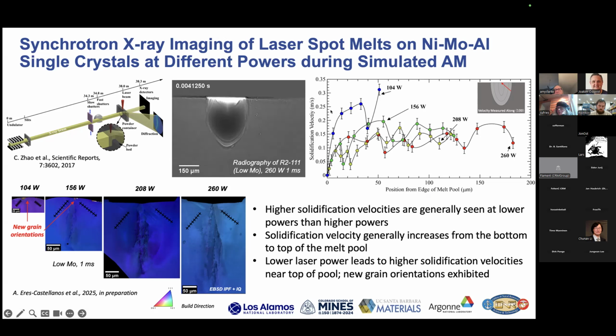So looking at velocity versus position from the edge of the melt pool for different power conditions, some trends fall out. For higher power conditions in general, we tend to see lower velocities. Where we have lower power, we tend to see higher velocities. And we do tend to see higher velocities towards the tops of the melt pool.